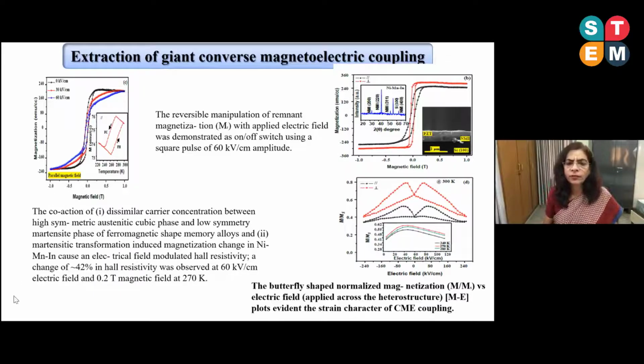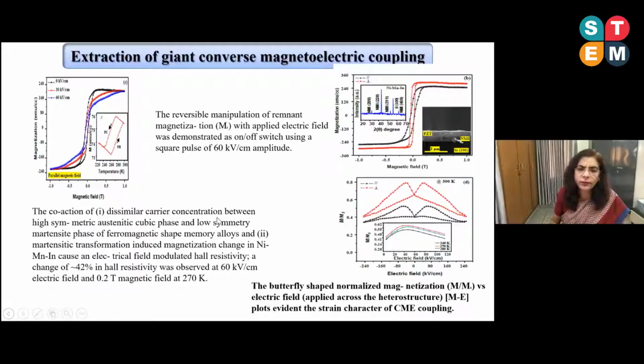The coaction of dissimilar carrier concentration between the high symmetric austenite cubic phase and the low symmetric martensite phase of the ferromagnetic shape memory alloy, and martensite transformation induced magnetization change in FSMA, causes an electric field modulated Hall resistivity. A change of 42% Hall resistivity was observed at 60 kilovolt per centimeter electric field and 0.2 Tesla magnetic field at a temperature of 270 Kelvin.